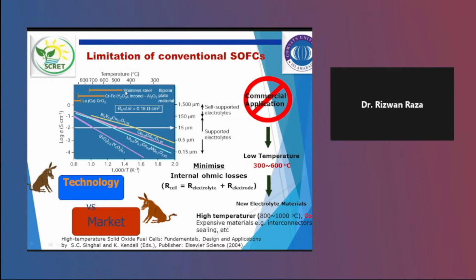Here is a comparison of different conventional electrolyte materials. Actually, anode, electrolyte and cathode, the electrolyte is a key component. If you can succeed in getting a good electrolyte which can operate at low temperature with a good conductivity, then you can prepare compatible electrodes. So first you have to think about the electrolyte material. Among electrolytes, yttria stabilized zirconia is very common and now commercial, but again it is working at high temperature. Every material has its own benchmark and required parameters.